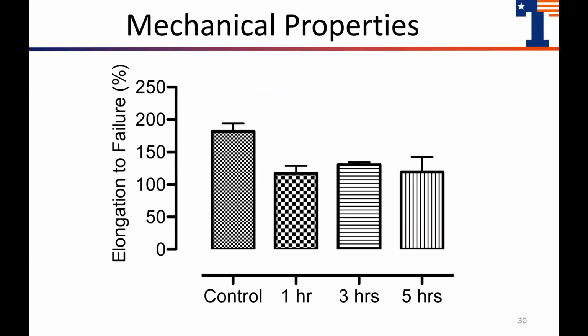So lastly is the elongation to failure. You can see there's a decrease between the control and the 1, 3, and 5 hours, but between the 1, 3, and 5, it's relatively unchanged between the times. So the original decrease from the control to the 1 hour indicates that the PLA fibers are actually becoming more brittle after they're being exposed to the hydrogen peroxide vapor. However, the increase of exposure time has very minimal effect on the elongation to failure.